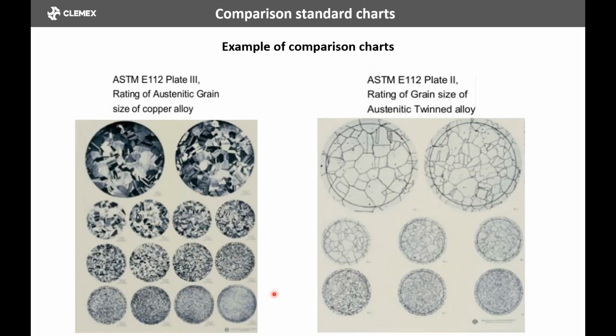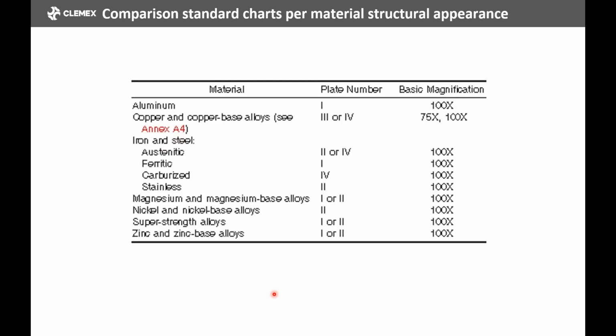Now, if we look at the comparison chart, we can see that there are various types of charts for various structures. Of course, you need to choose a structure that is representative of your material. So if you have twin grains, you have to use plate 2. And if you have this example of a copper alloy, you would use plate 3. If we look at what the standard says, we have a variety of plate numbers, 1, 3, 4, depending on the material. Nickel alloy base will be 2, and normally the reference is based on 100x magnification. That means that if you're looking at a chart, you have to look at 100x to have a comparative magnification.